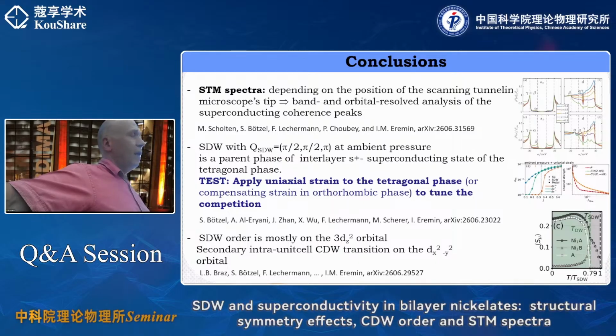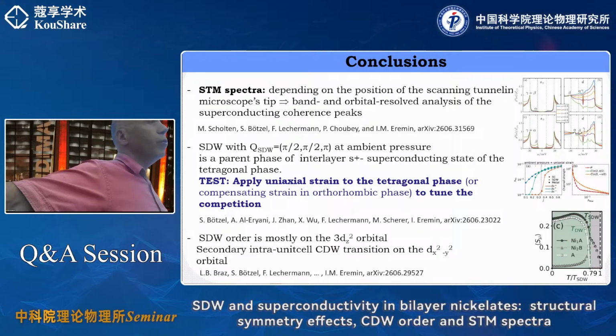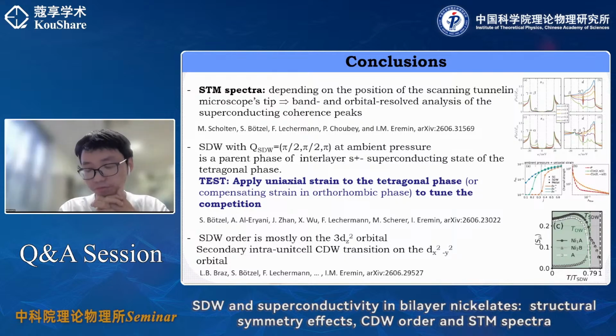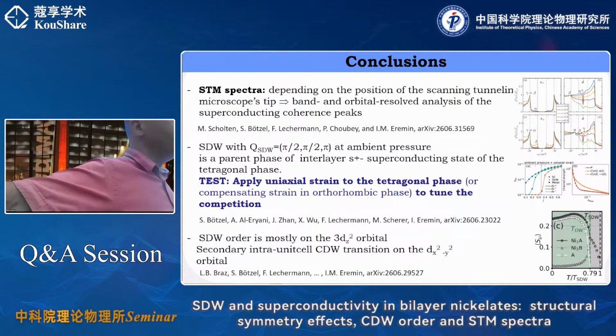Let me put it like this. We just argued, I don't know whether you picked it up, but we just agreed that to some extent there is a similarity. If you look at the orthorhombic phase, then the magnetic wave vector is 0 pi. If you take a double Q of it, you will get a 2 pi. So this will be exactly this intra-unit cell order, because 2 pi is a reciprocal wave vector. In this regard, this intra-unit cell order is the same double Q that you have in a trilayer, with the only difference that in a trilayer, the original magnetic wave vector is incommensurate, such that you can still create a 2Q of this, and it will not be a Q equal to 0. Here it is not.